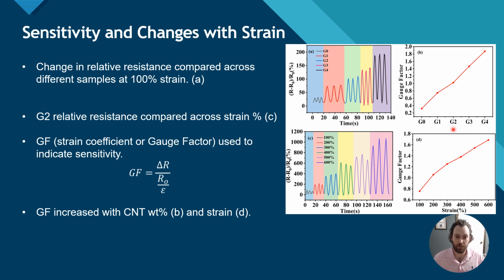We took a sample listed below from G2 yet again, and we then elicited different amounts of strain and compared the relative resistance change with the amount of strain, and found that with increasing strain, we had an increasing relative resistance from 100 to 600%. And yet again, a linear relationship with the gauge factor versus the strain percent.